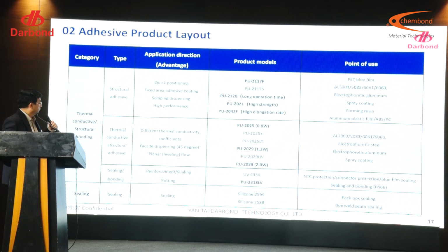So on the third column, you can see for those different functions, we have different material recommendations. For the different materials, you can use them at different locations during the process. For example, PET blue film. If you are a packaging engineer, you're probably familiar with that. And aluminum alloy, electrophoretic aluminum, spray coating, forming resin, aluminum plastic film, ABS and PC or whatever. Those are the points that have to contact with the adhesives.